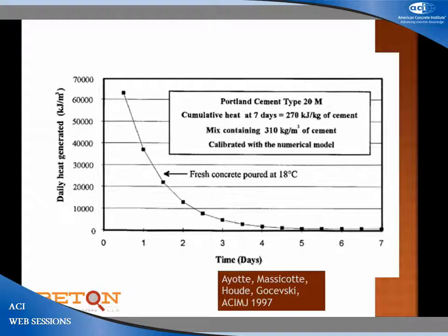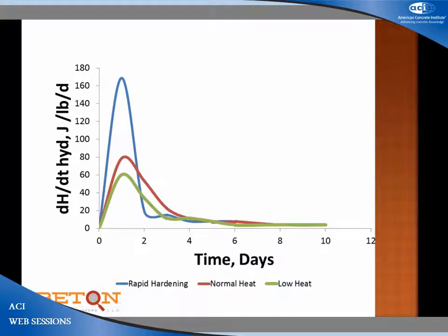Now, the best part is that under modern analysis, we can take those curves and convert them into heats of reaction. This is the heat of reaction for the data in the first paper in the 1930s, at about 160 joules per pound per day. That's what we call a bastardized unit: joule, Systems International; pound, the common engineering system. Those of you who didn't study chemical engineering won't know that you measure weight in slugs anyway.